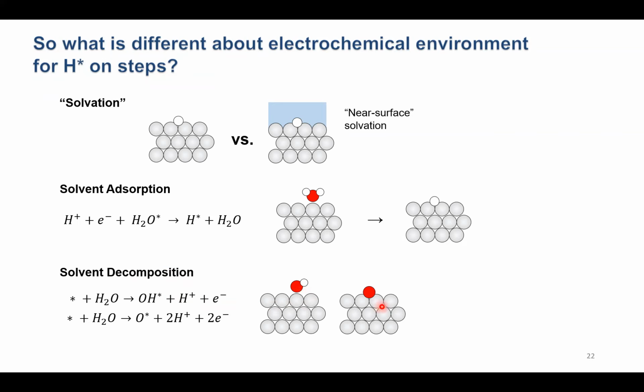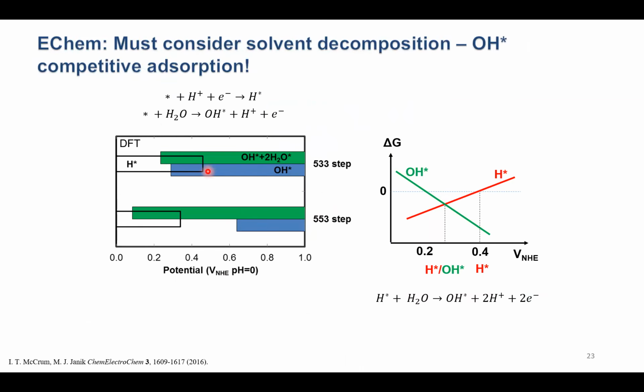And so we've looked at all of these options with density functional theory. And what we found is that we needed to consider solvent decomposition. What we find is that the stepped platinum sites not only bind hydrogen very strongly, but also bind hydroxide very strongly. And so what I'm showing here, the end of each of these bars represents the equilibrium adsorption potential for hydrogen and for hydroxide. Because hydrogen adsorption is a reduction reaction, it becomes more favorable as we go to potentials lower than that adsorption potential. As hydroxide adsorption is an oxidation reaction, it becomes more favorable as we go to more positive potentials. We can see that here if we plot the delta G versus potential. The equilibrium potential basically represents where this delta G crosses zero.